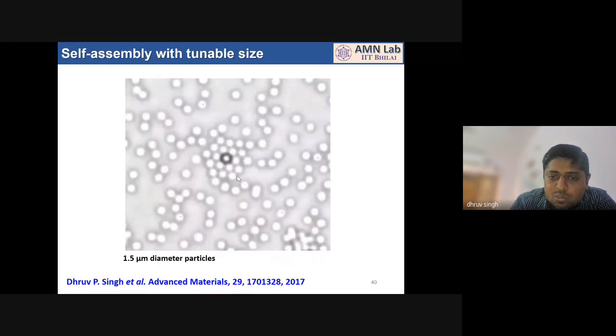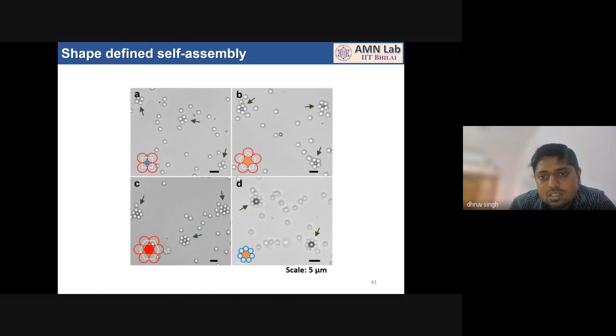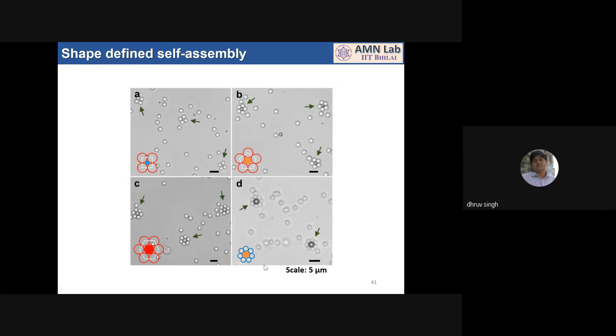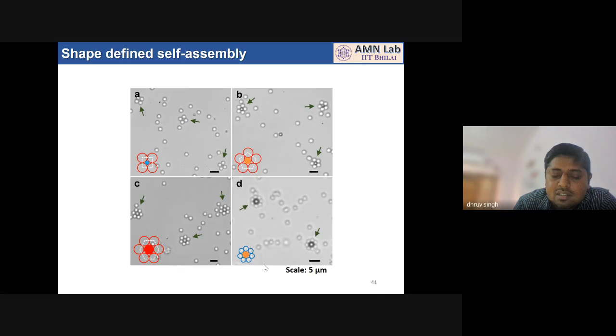So once you know how to control the size of the structures, the shape of the structures can be further controlled by carefully selecting the size ratios of the nanomotor and the surrounding passive particles. Like you can form the square, pentagon, hexagon, and heptagonal shapes. Here, the shape of these structures is formed by a simple rule: how many passive particles can be fit in a closed shell around a single active particle, or single nanomotor. So this is the closed layer. You see, this is the closed layer.